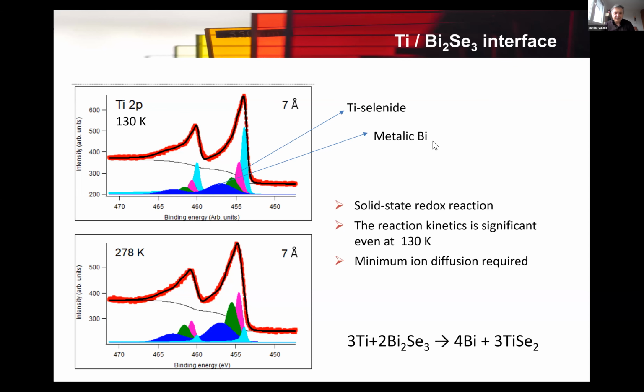Now, if I write down this reaction schematically, the overall reaction, we can see that from metallic titanium we produce titanium selenide, and from bismuth selenide we produce metallic bismuth. Actually, it is a redox reaction, when titanium gets oxidized and bismuth gets reduced.